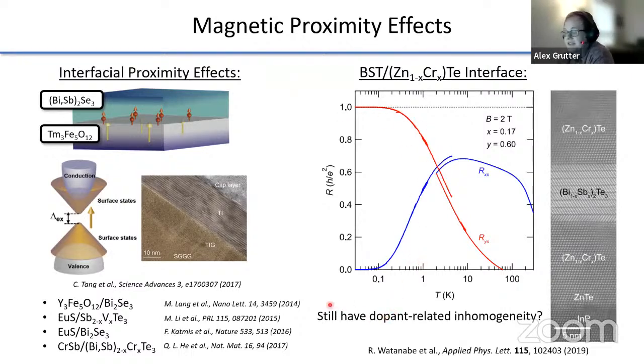And it has been suggested that this might be because you're still experiencing dopant-related inhomogeneity in this system. So the idea being, okay, well, now you no longer have chromium dopants that are randomly dispersed in the bismuth antimony telluride, but instead they're just randomly dispersed in the zinc chromium telluride. This may or may not actually be the reason for the low transition temperature. We don't really know yet. It could be that there are other explanations, but